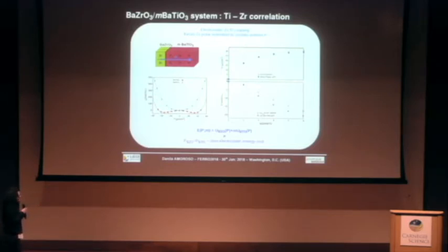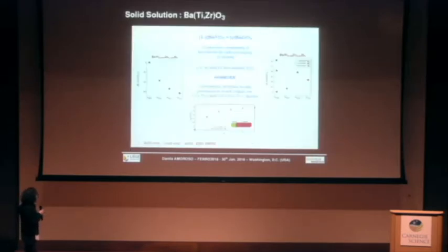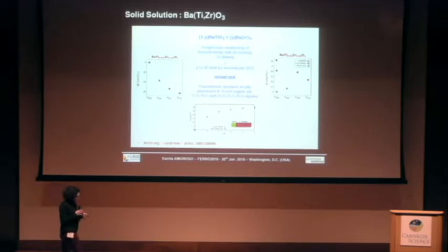And so we can also interpret this as the fact that we are able to lower the energy cost to polarize barium zirconate by adding several times the energy gain that we get when we polarize barium titanate. When I say several times, I mean several times the number of unit cells of BTO that are following barium zirconate. And in this case, already 2 unit cells of barium titanate are enough to develop the homogeneous polarization.